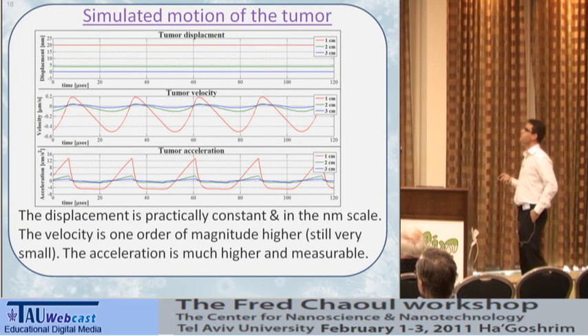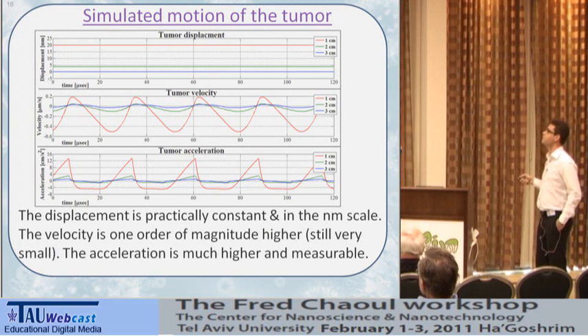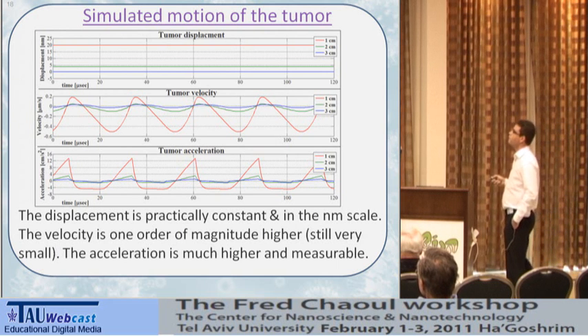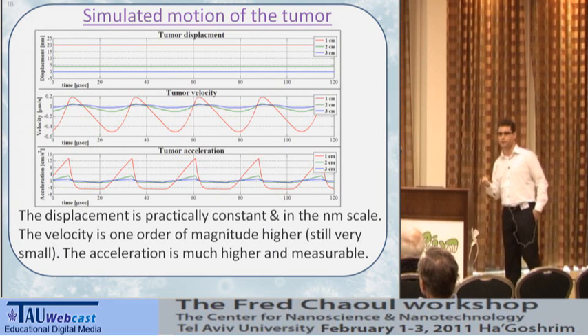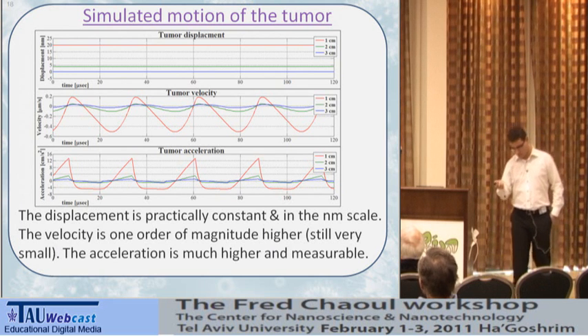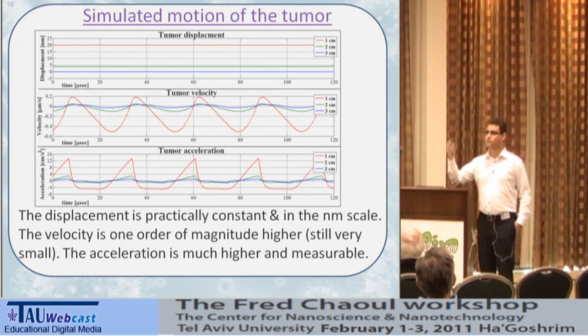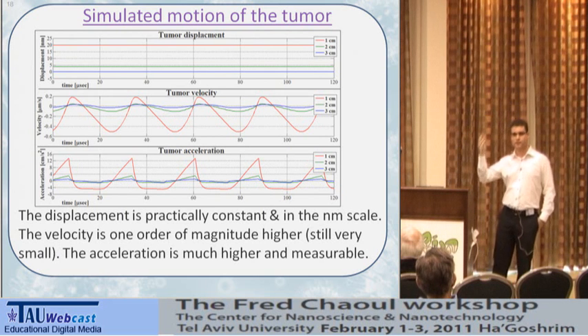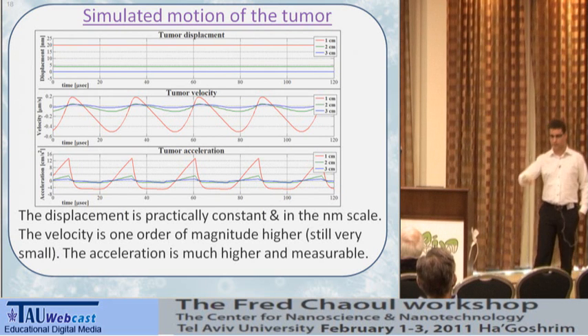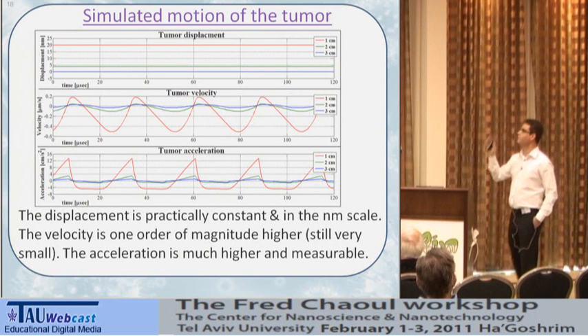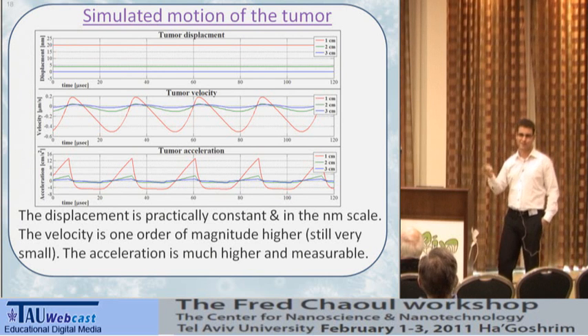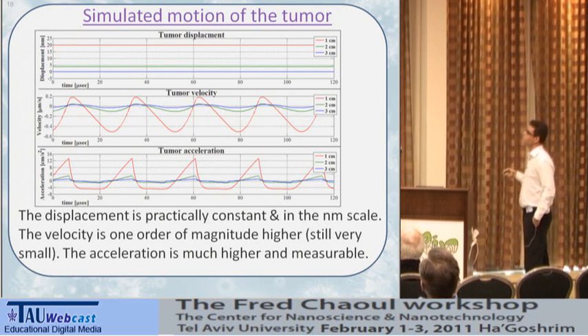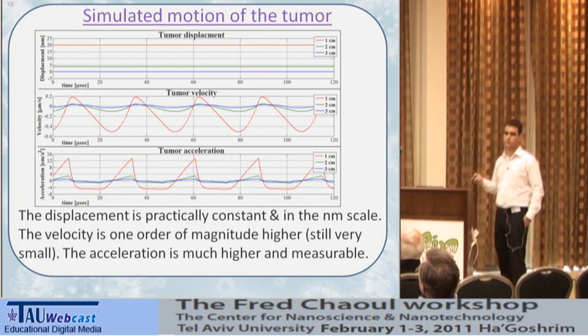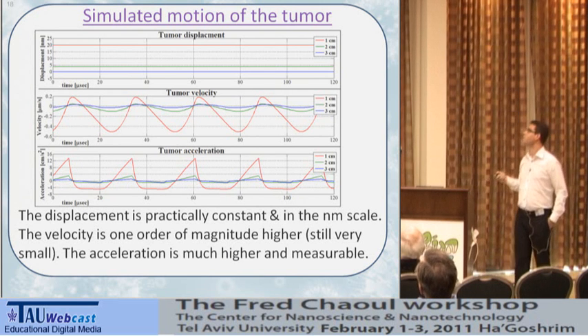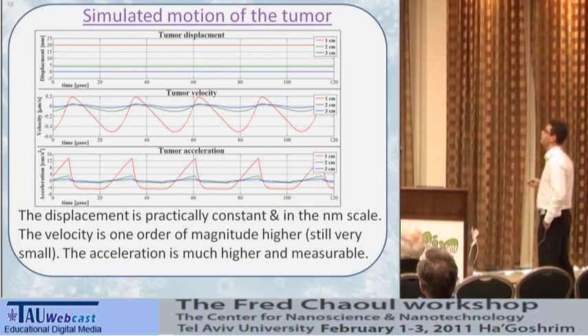Some of the simulation results: we look at the tumor displacement, velocity, and acceleration. We see that the displacement is very, very small. It's on the order of nanometers. And it makes perfect sense because you can't move things a lot inside the tissue without the tissue reacting and restoring them back to place. There are elastic forces. So movements of 20 nanometers or so are very sensible, are fine.